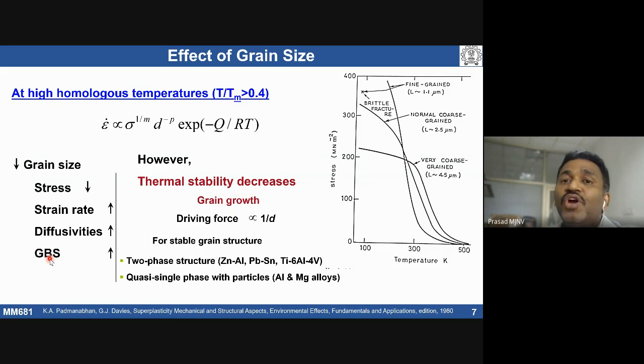That's why we do not see superplasticity in pure metals. Superplasticity can be observed only when there is a stable grain structure. That's why I said we need to have a fine, stable grain size. That can be obtained in the case of two-phase structures and quasi-single phase structures with particles, when there are precipitates. Alloys which contain precipitates can exhibit superplasticity because we need to control the grain growth. You have to pin it down. So two-phase materials and quasi-single phase materials which contain precipitates can exhibit the superplasticity phenomenon. Is it clear?